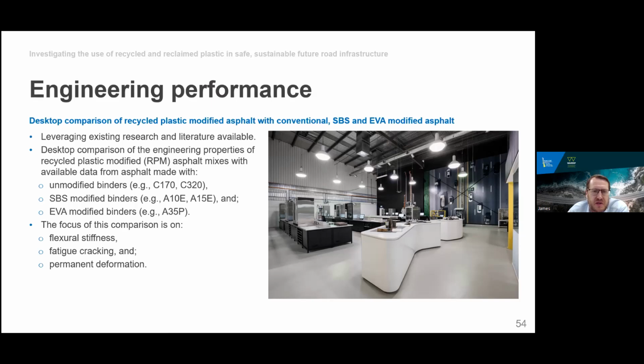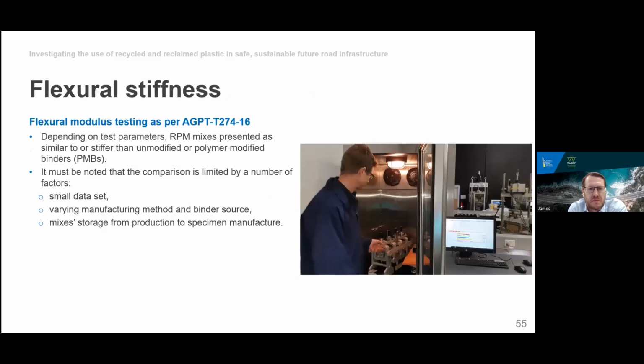So the focus was looking at, obviously, the data available on recycled plastic modified asphalt mixes, but also comparing that with published data on unmodified binder mixes, so C170, C320 binders, or even C600 binders in asphalt. SBS modified binders, so the A10Es, A15Es, and EVA modified binders in asphalt, such as A35P. And the focus of this comparison was on flexural stiffness, fatigue cracking, and also permanent deformation of the resultant asphalt mixtures. Next slide, please, Chrysoula.